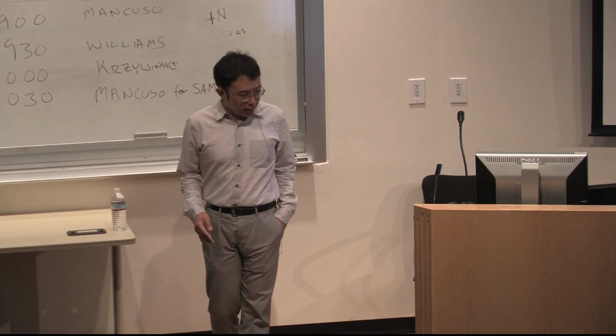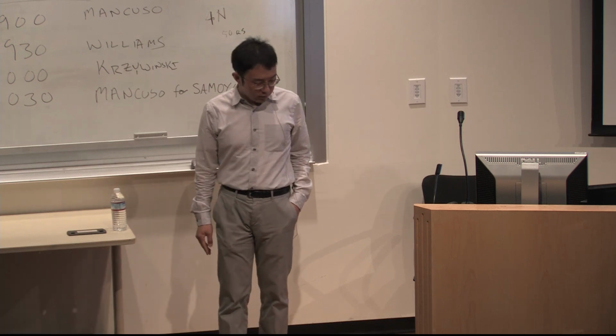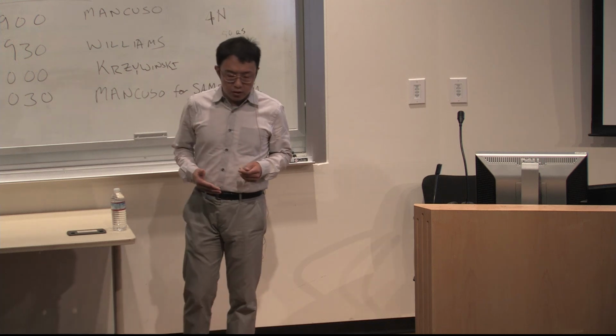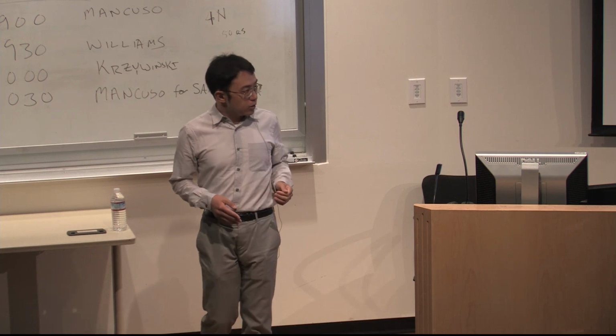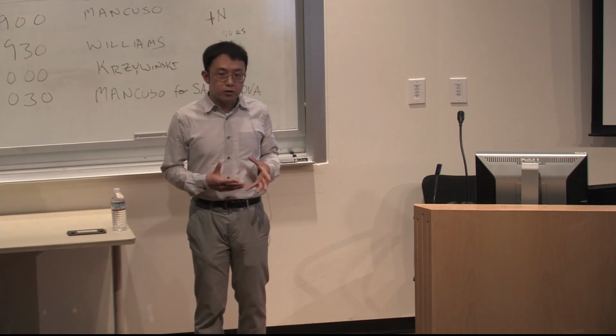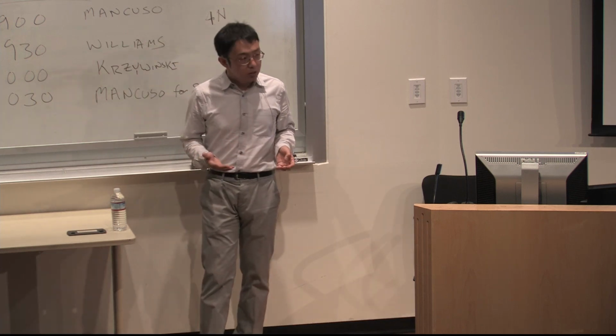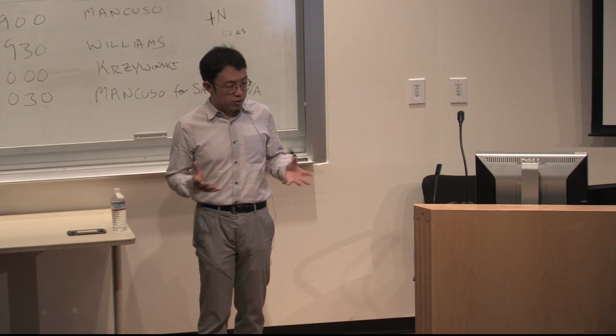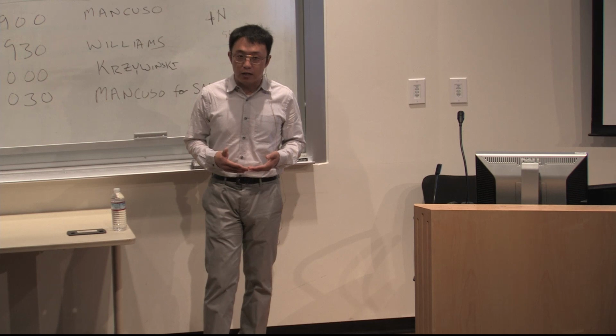It's quite stable. And the other thing that I want to bring up along this line is that this diamondoid coating actually stabilizes some of the normally unstable chemical valences. For example, in one of the copper sulfide structures that I showed you, the copper is in the copper 1 state, which is normally unstable in air. It turns into copper 2 very quickly. When you have the diamondoid surrounding them, it stays in copper 1 for a very, very long time. We don't see any degradation of it. So in a sense, the diamondoid, like a shell, is a protecting agent that actually stabilizes the semiconductor core in there.